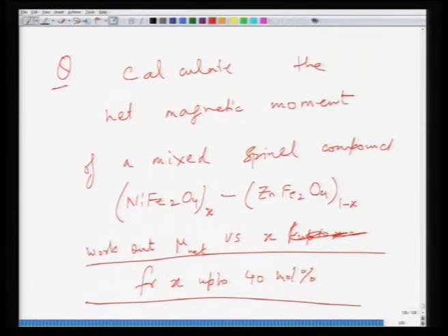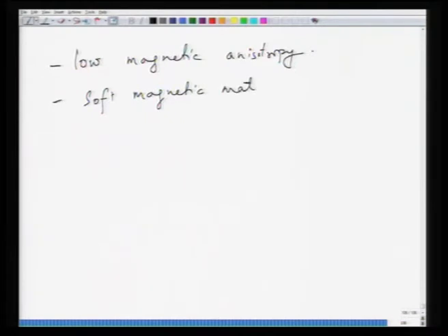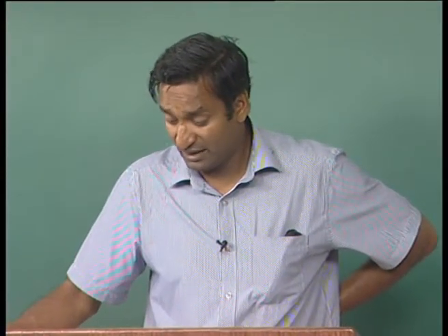Okay. Another thing that you find in cubic spinel ferrites is that they have low magnetic anisotropy, which means they don't have a strong dependence of magnetization on the crystallographic direction. So as a result, they are magnetically soft magnetic materials. So they don't have large hysteresis losses, and some of the exceptions could be cobalt containing ferrites, which tend to have somewhat large magnetic anisotropy, and they also have very large coercive field strength. So they could be exceptions.